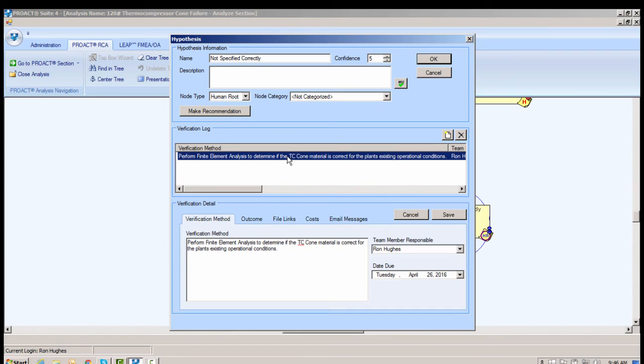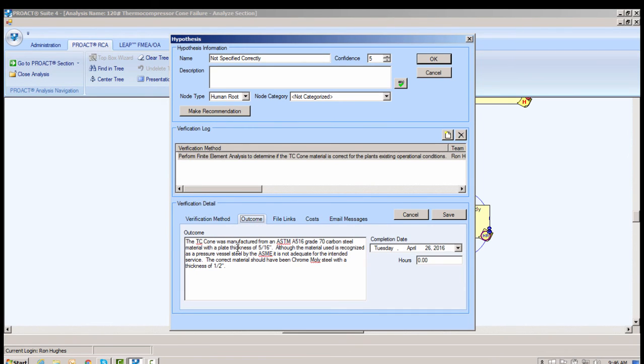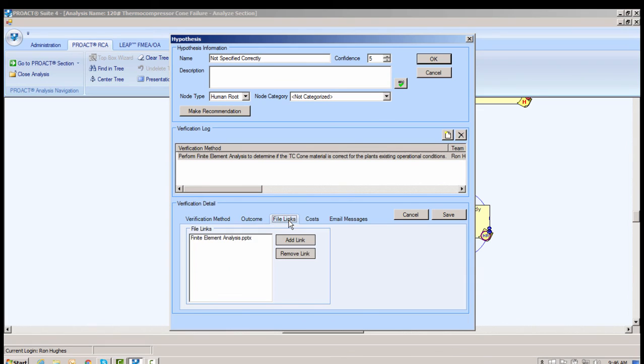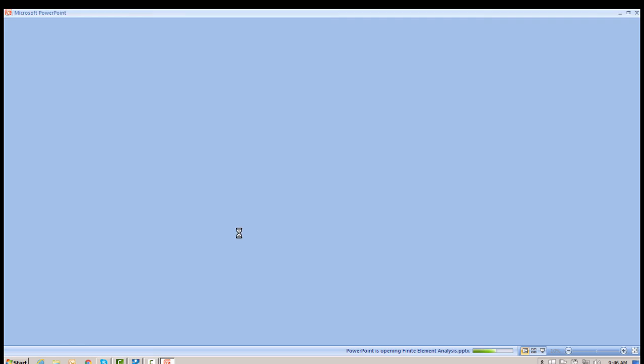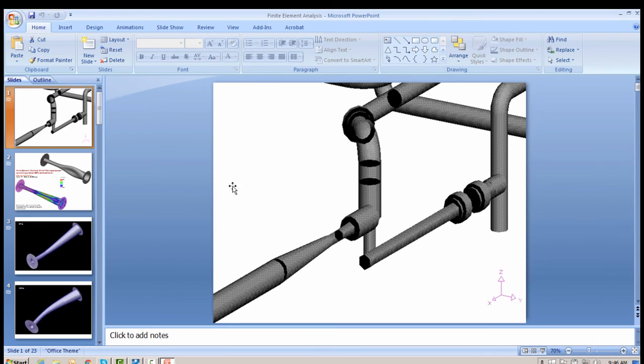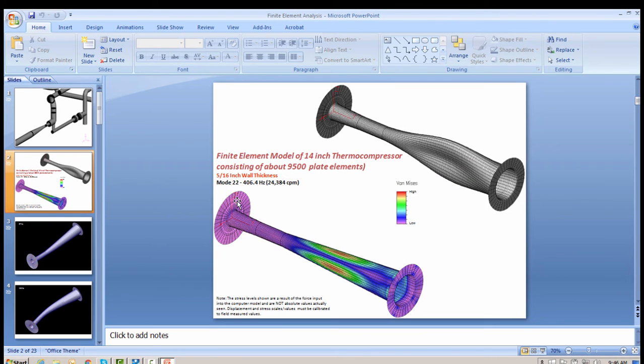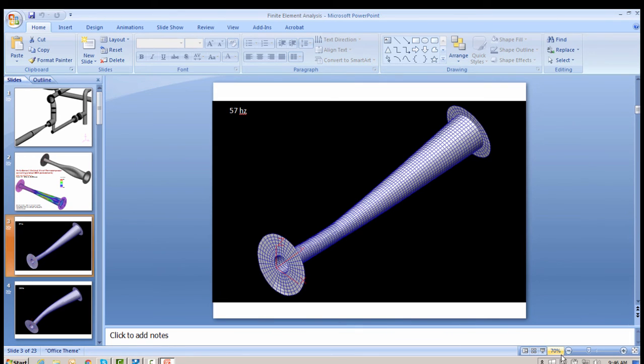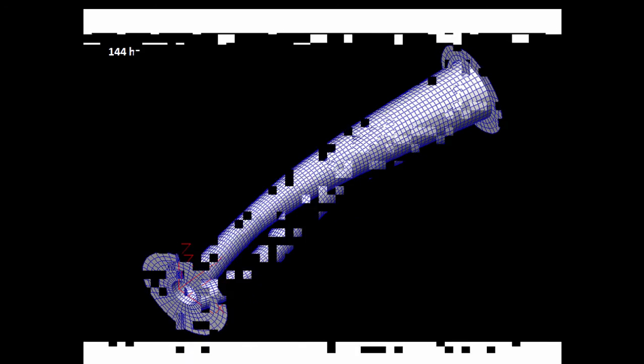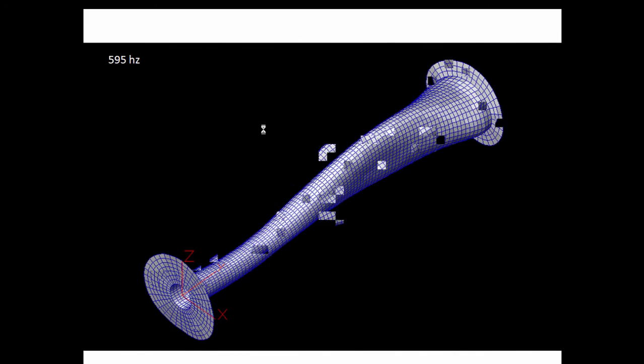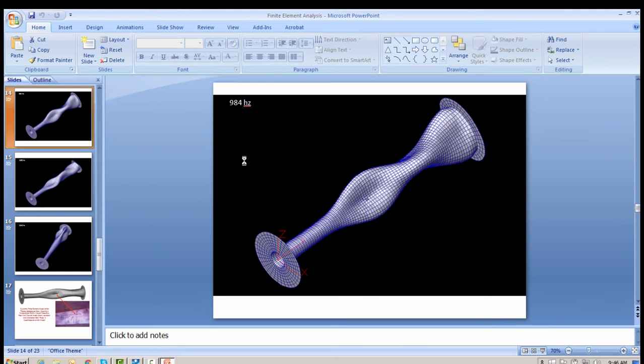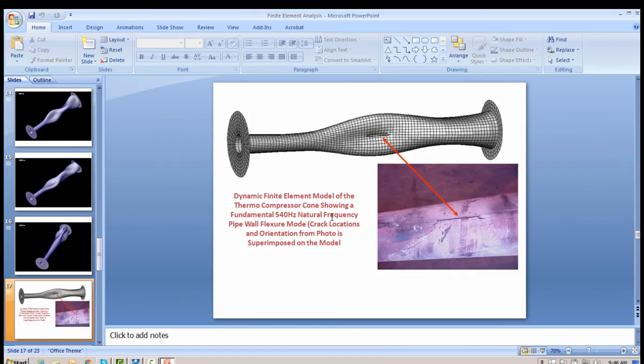We do a finite element model on it, and what we find is that the material used is not adequate for the service that we're seeing. And let's look at this. This is where we're modeling it, and we model it in 9500 plate elements. Of course, the areas of lavender are areas of very low stress, and the areas of red are areas of very high stress, and we can look at the deflection shape. And this is what we found in our model.